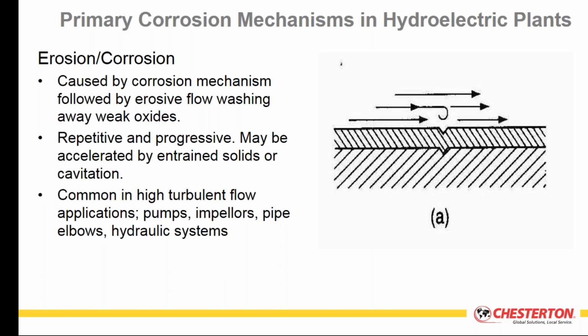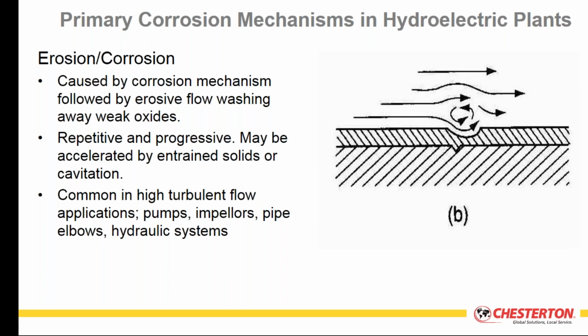When you see the event and how it occurs, it is a progressive approach. In the first image here, you see the weak oxide layer on the surface. You see the flow, which is more laminar in nature now. When that is moving, it's gently across the surface, not so aggressive. But if you start to generate some minor areas of attack, these begin to create some turbulent flow. And as the turbulent flow accelerates, you start to see an accelerated rate of removal of that weak oxide layer.